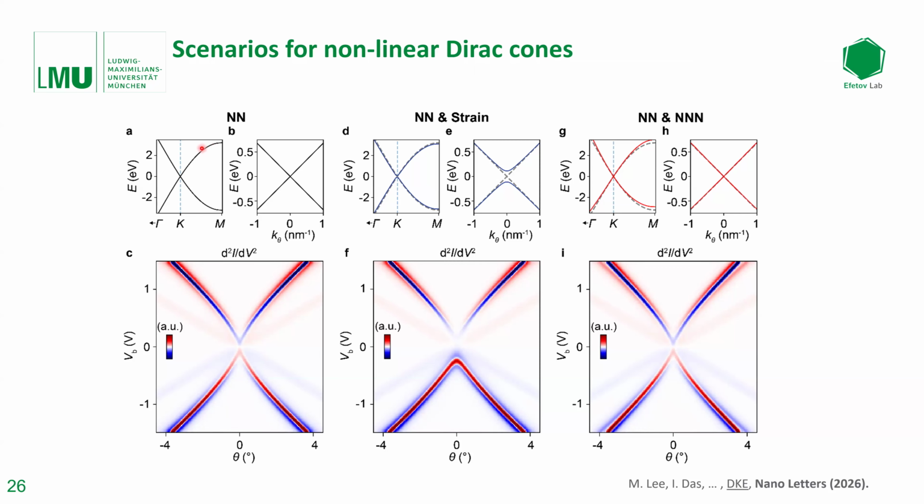So the question was whether this nonlinearity at higher energies could be the one we're seeing. And actually, we found that this cannot explain the features, because we would expect this nonlinearity to set in at much, much higher voltages than what we are probing. So basically, we were a factor of 5 off in the voltages that we were obtaining.